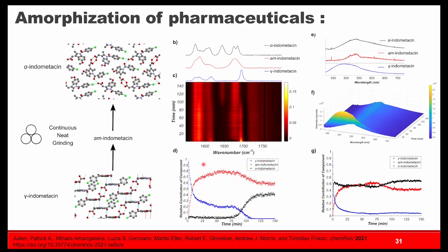And so we can actually see here gamma indomethacin, the amorphous. And it's interesting that we have this dynamic where you have the amorphous as well as the gamma phase coexisting for a time. And then all of a sudden you have almost like a nucleation of the alpha form, but it doesn't completely convert. We still have a lot of amorphous indomethacin. And where these in situ techniques really shine is that by the time I take this reaction out and do any sort of characterization, the end product is always 100% alpha indomethacin.